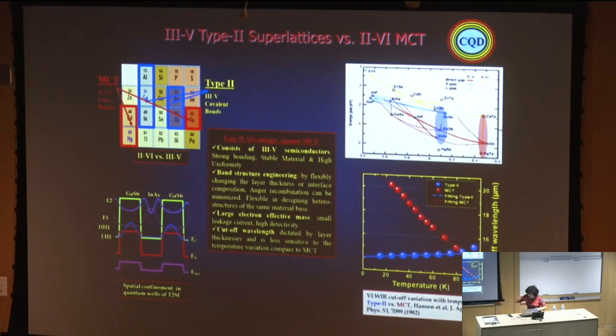So what does it mean? It means that by changing one monolayer, you can change the gap, and for one wavelength, you have many different ways to manage that. And at the same time, you can go to very short wavelengths, 3 to 32 micron, but the effective mass is exactly the same, indium arsenide, gallium antimonide, only you change the thickness. So you can see that there is physics behind it already, you can have much better performance for the dark current by comparison to mercury cadmium telluride.